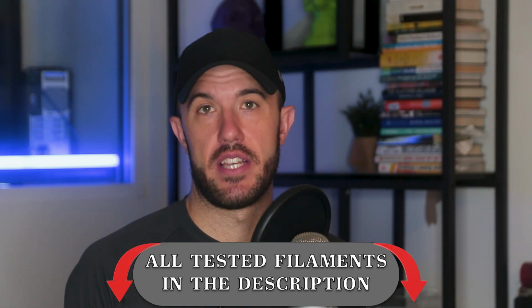Carbon fiber sounds really good, and it has lots of benefits. It has better surface finish, it can have better abrasive resistance, and it can have some good impact properties when you design the part right, because you're creating something that is potentially more durable. But carbon fiber is much more of a buzzword than anything else. It does not improve the overall strength of the part, as many people think that it does. It is kind of gimmicky, and it can actually hurt the part itself by just breaking up the actual interlayer adhesion of the pieces. So we'll continue testing these and adding new variations of the tests over time.